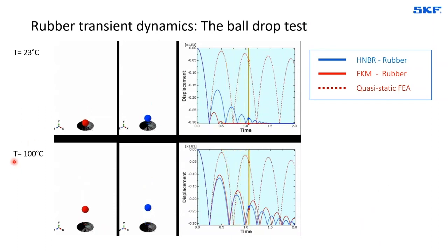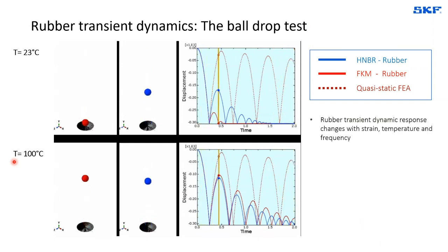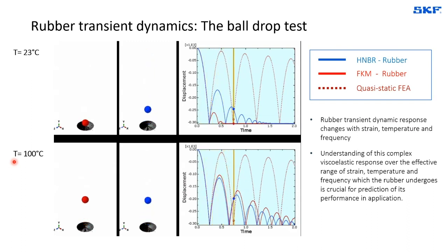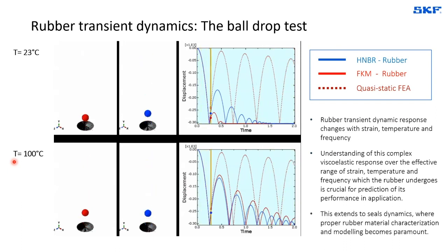Finally, to answer the question at 100 degrees centigrade, what is very interesting is to see that the two balls then suddenly behave very similarly. And this is because, of course, the loss factor shifted at a higher temperature is nonlinear. And then what happens is that the two balls depict a similar loss factor for that temperature, leading to the result that we see on the slide. So it becomes very clear here that understanding rubber transient dynamics with the effect of temperature and frequency is a must, because the understanding of this viscoelasticity and the effect of strain, temperature and frequency allows us to capture the very nature of the rubber response. And this is, of course, paramount for anybody that wants to understand in detail and with accuracy how seals react in dynamics.